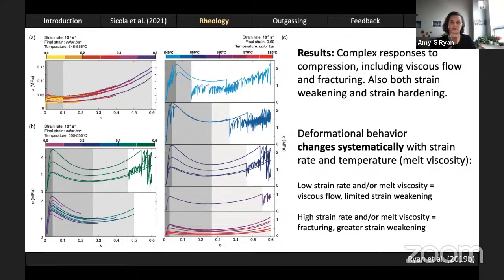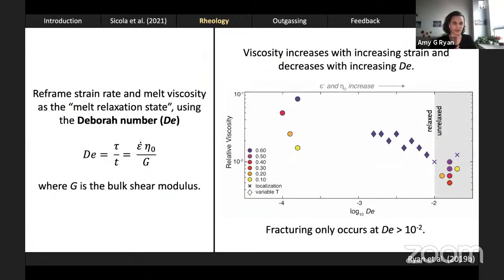Because I know deformational behavior is inherently linked now to strain rate and melt viscosity, I wanted to combine those two things into a single parameter just to make my life a little bit easier and get a better chance of interpreting what's actually going on in this material. So I reframed strain rate and melt viscosity into a single parameter, the Deborah number, which in this case represents the melt relaxation state.